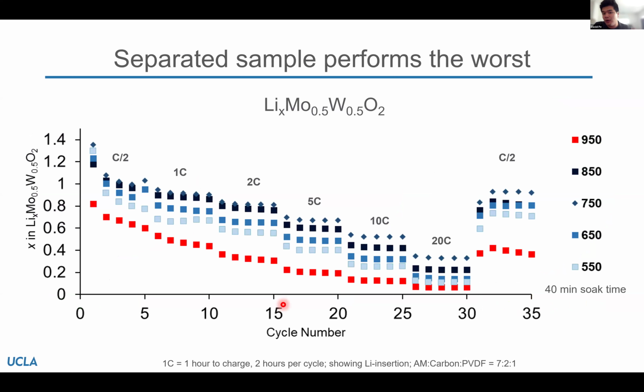And so just to show a little more battery cycling here, the main takeaway is that we have these solid solutions that are made in an identical way, except the only thing we're changing is the temperature that we synthesize them at. And we can see a trend where we start at a low temperature and we crystallize our material, where it peaks at 750 degrees. Crystallinity is good for enhancing lithium ion diffusion kinetics, so faster charging and discharging. But past that point, the higher temperature starts to encourage phase separation, and we see a drop in performance all the way down to when we heat them up at 950 degrees, where they perform quite poorly at not just fast rates, but slow rates too. And again, this is just to demonstrate that notionally identical materials can have very different performances as electrode materials, depending on their local phase separation.